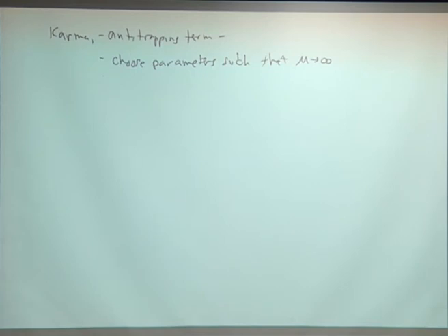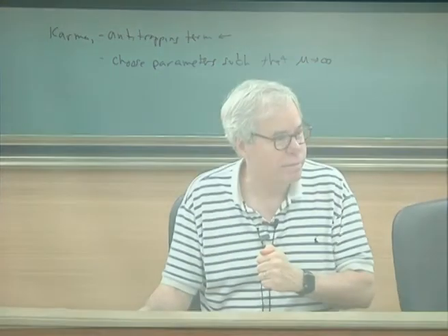The other thing that I'll mention about this, which is kind of an interesting sidelight, is that when you put in the anti-trapping term, the phase field equations are no longer variational. The total energy of the system is no longer minimized as a function of time. It actually goes up. But the reason why you know it works is because you get the sharp interface equations. So the asymptotics say you get the sharp interface equations. The actual evolution equations violate the first and second laws. And this anti-trapping term is embedded in just about every kind of commercial phase field code now because of all these problems.